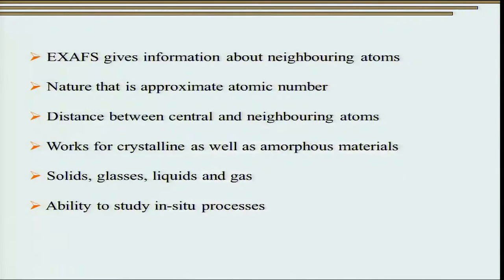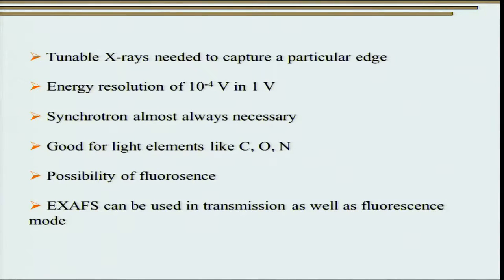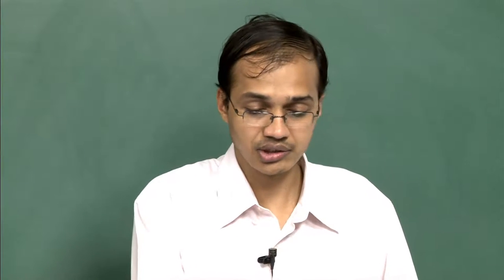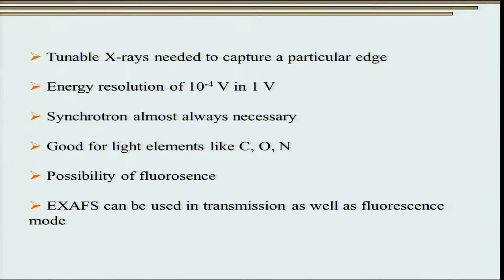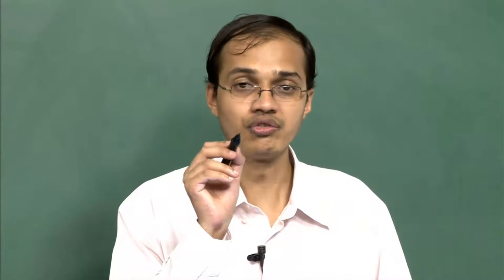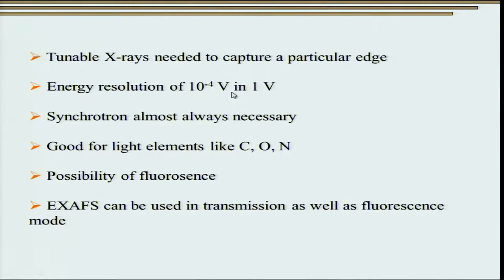XAFS can also be used for studying solids, glasses, liquids, and even gases. One of the biggest advantages is in studying in-situ processes in different classes of materials. However, XAFS is not as common as other spectroscopy techniques like EDS, mainly because we need tunable X-rays to capture a particular edge. We also need a very good energy resolution of the order of 10⁻⁴ V in 1 V, and therefore in most cases we have to use a synchrotron source for carrying out XAFS studies.